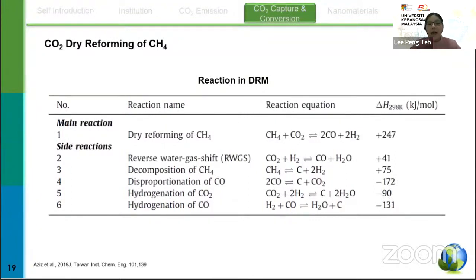For your information, the DRM, or dry reforming of methane, is thermodynamically viable only at very high temperature, about 700 degrees C. This high temperature will promote DRM and inhibit the side reaction. But from the economic and technical perspective, it would be more beneficial if we can lower the temperature of the DRM to below 700 degrees C. By doing this, we need a very stable, very active, and very selective catalyst to be introduced in this DRM reaction system.